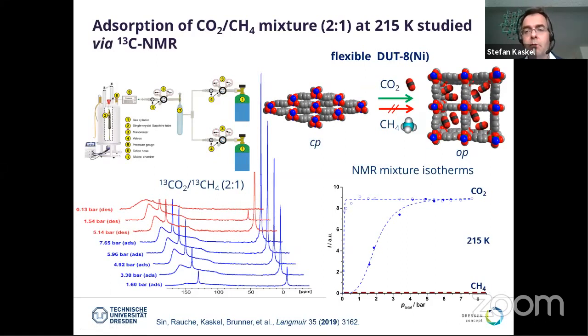This is maybe a bit brief without too much introduction, but what we are basically doing is dosing CO2 and methane into the capillary. It's a sapphire capillary where the MOF is located. And we are measuring the signal of the CO2 and of the methane in the capillary. What is interesting in this case is that you can see the CO2 and methane in the gas phase. This is this very sharp signal here. Actually, the pressure is recorded here. The blue is adsorption and the red is desorption. So you can see the free gas, which is not in the MOF, as a very narrow signal.